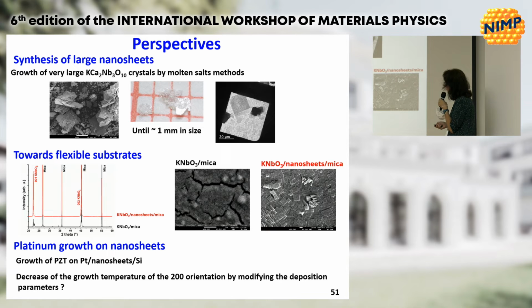Concerning the platinum nanosheet growth, the next step now will be to grow an oxide on the platinum nanosheet silicon stack to see what happens, and also to try to decrease the growth temperature for this 200 orientation by modifying the deposition parameters.